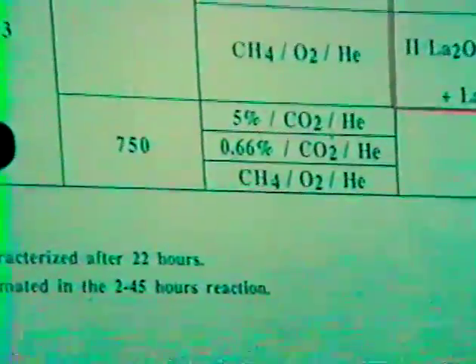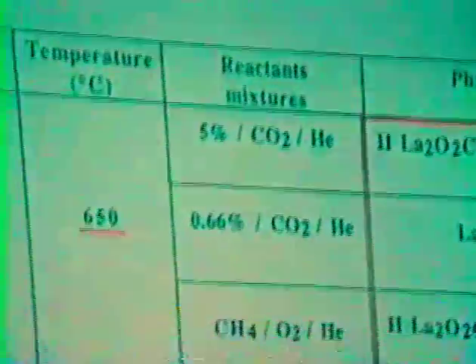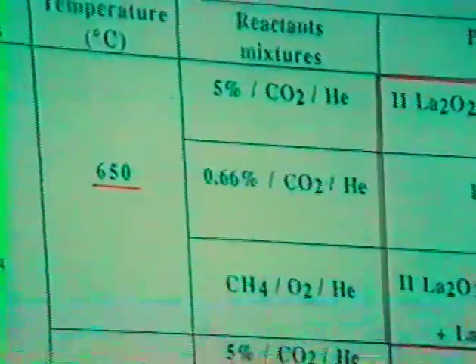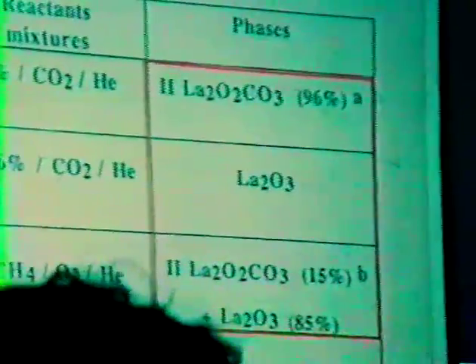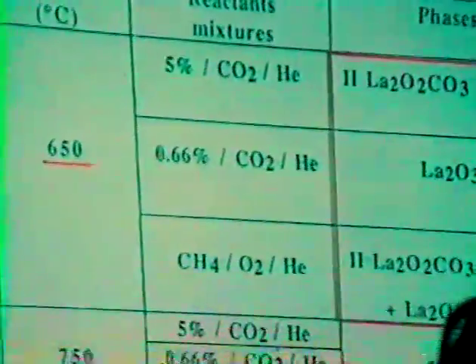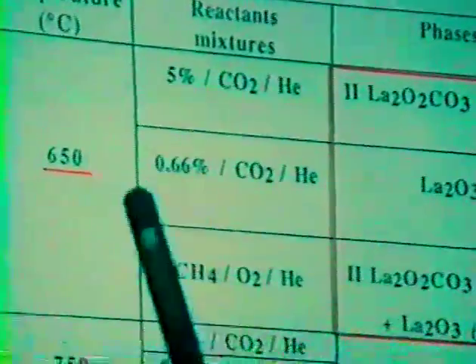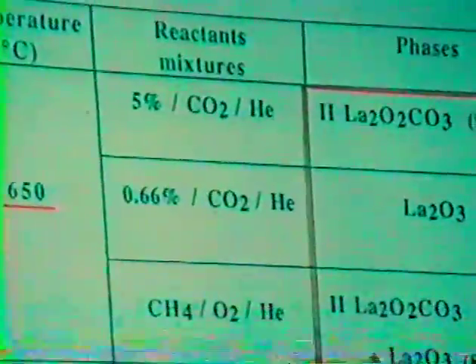So here I have summarized the phases which were observed. At 750 degrees, there is no formation of the oxycarbonate. At 650 degrees, using the 5% CO2 mixture, you observe almost a complete transformation into the oxycarbonate. This is a curious result: when you use the 0.66 percentage corresponding to the lower partial pressure, you do not observe the formation of the oxycarbonate.